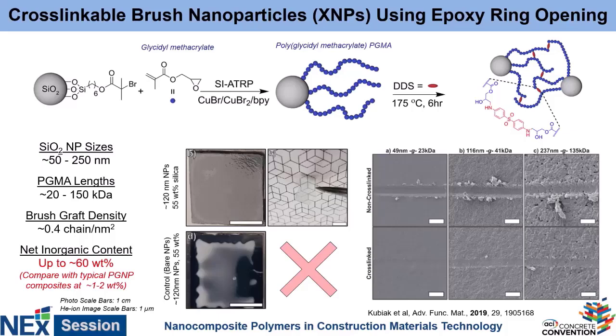After cross-linking, the material becomes much, much more scratch resistant. In fact, these are helium ion microscope images — not standard SEM — because when we took these scratches to the standard SEM and tried to find them, we couldn't find them. They're basically so scratch resistant that the scratches were almost impossible to find. This is a much more mechanically robust material that could be useful for things like coatings for glasses, lenses, or other materials, because it remains transparent even though it's mechanically very hard.